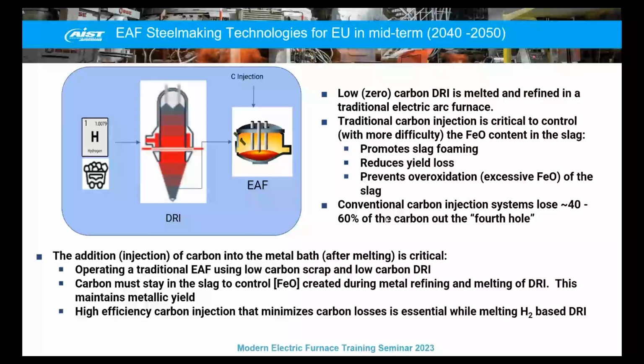This is just a summary in the end: that low carbon DRI melted and refined in electric arc furnaces still requires injection carbon. You still have to have foamy slag in an electric arc furnace. There might be alternative means in the future for foaming slag, like biocarbons and things like that coming around, but largely you'll need some type of carbon units going into that slag in order to get it to foam.